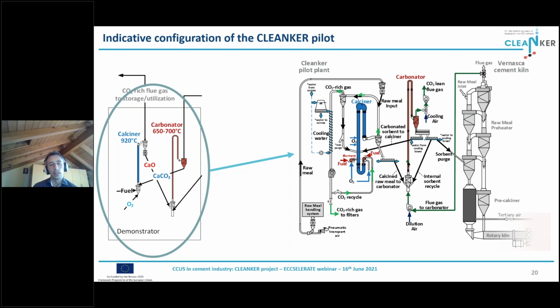For instance, you can see that the carbonator has also the possibility of recycling some of the sorbent from the carbonator outlet to the carbonator inlet to improve the capture efficiency of the carbonator without increasing the energy consumption in the calciner. The calciner is equipped with a preheating stage, again, a riser cyclone preheating stage similar to what we have in a conventional cement kiln. Again, this is for reducing the fuel consumption in the calciner. And also, still in the calciner, we have CO2-rich gas recirculation, which can be used to tune the properties of the oxidant mixture.